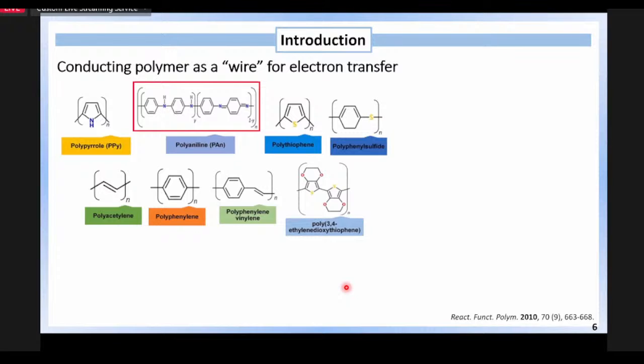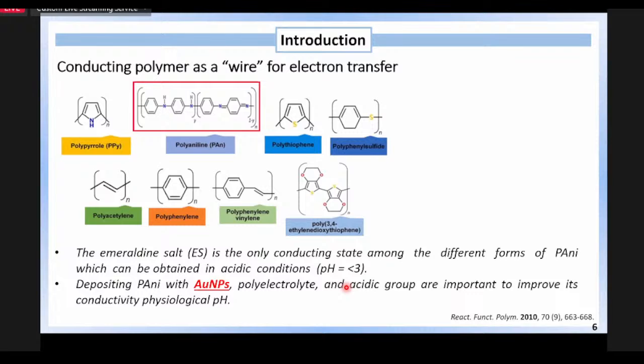And here in Park Sensor Laboratory, polyaniline is very useful and has been applied for several biosensor platforms. However, the limitation of polyaniline is that the emeraldine salt is the only conducting state of polyaniline, which can be obtained in acidic conditions, which is almost impossible if we want to construct an antibody-based biosensor in slightly acidic conditions. But we can modify the polyaniline and improve its conductivity by depositing gold nanoparticles or quantum dots or another moiety that could improve the conductivity of this polymer.